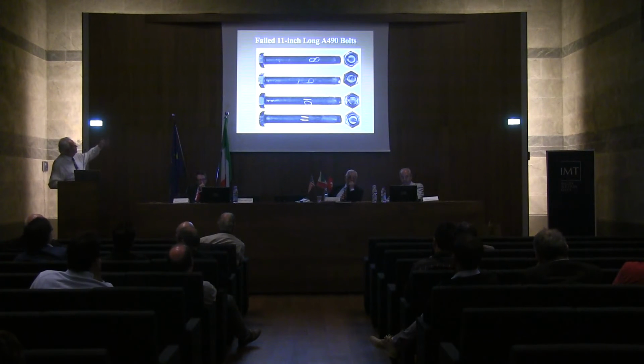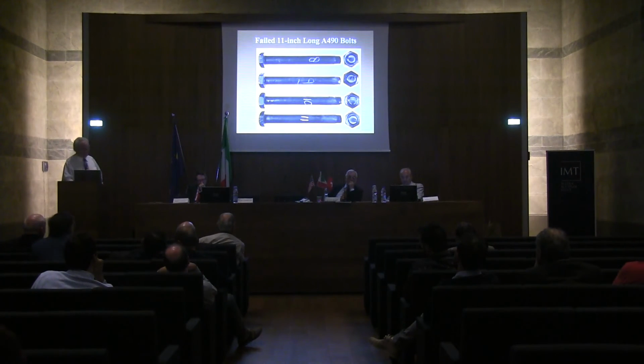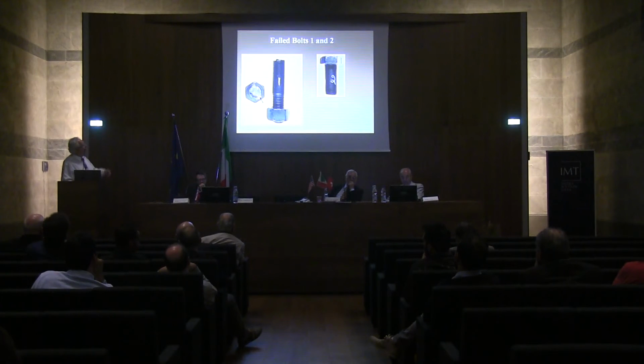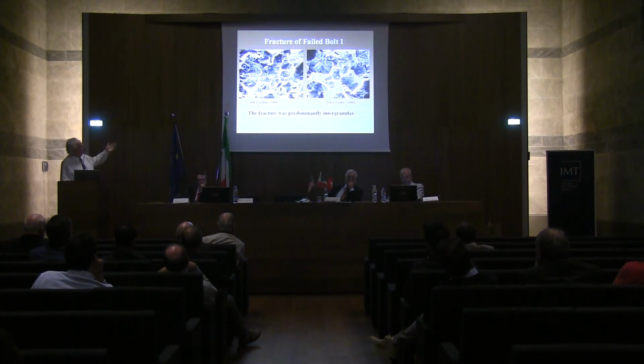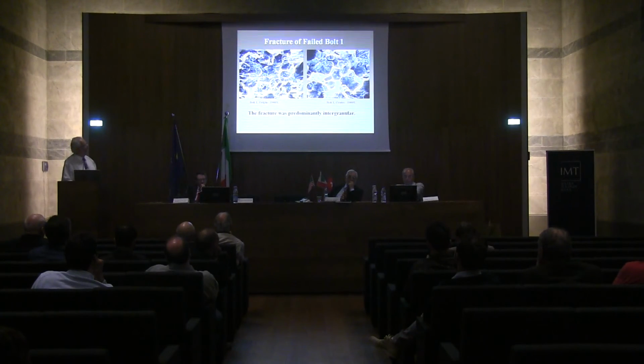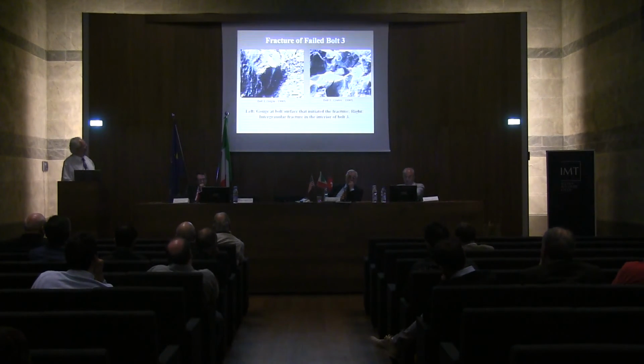Here are examples of some of these failed bolts. And you can see they're failing in the thread. It's usually the first thread that's engaged in the nut. Here's bolt 1 and 2 where you had these strange origin zones. And in bolt 1, you can see at the origin at 1000X, it's intergranular. And even the center of the bolt fractures predominantly intergranular. And there's some secondary intergranular cracking going off the main fracture.